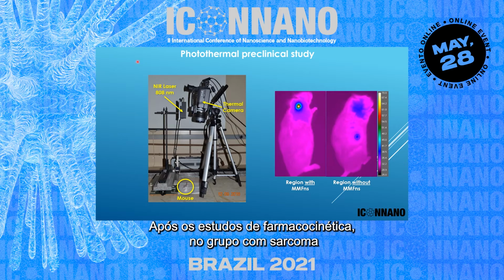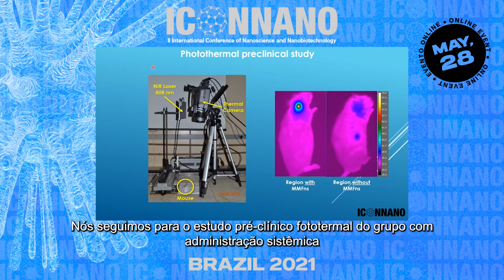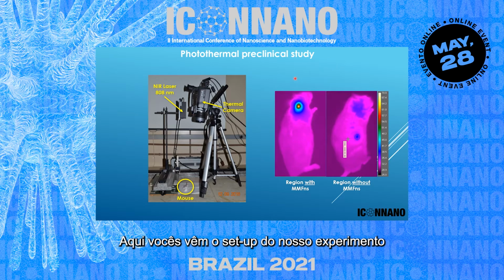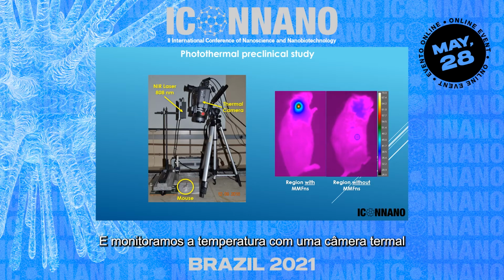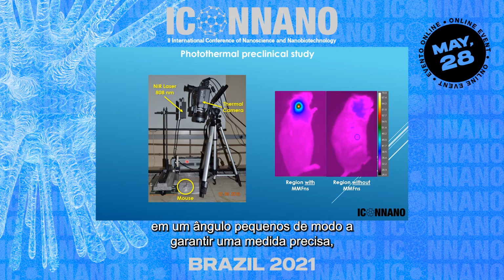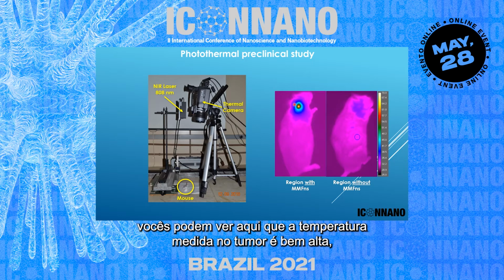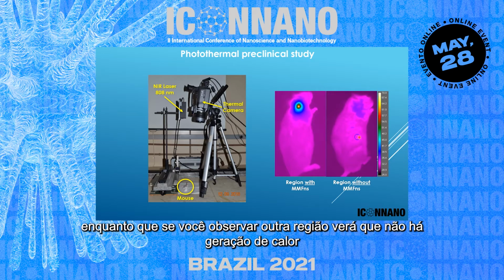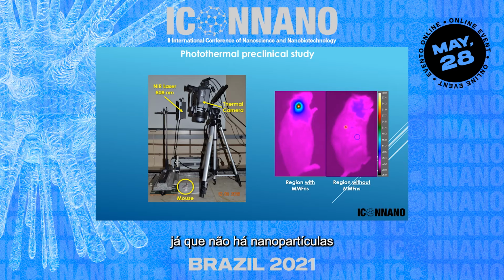After the pharmacokinetic studies in the sarcoma group, we decided to go for a photothermal preclinical study of the systemic administrated group. And what you're seeing here is a setup of our experiment. So you can see the near-infrared laser, you can see the mouse, and we are monitoring the temperature with the thermal camera with a very small angle in order to guarantee a precise temperature measurement. You can see here that the temperature measured in the tumor region is very high, while if you go in another region of the animal, there is no heat generation because there are no nanoparticles in that region there.